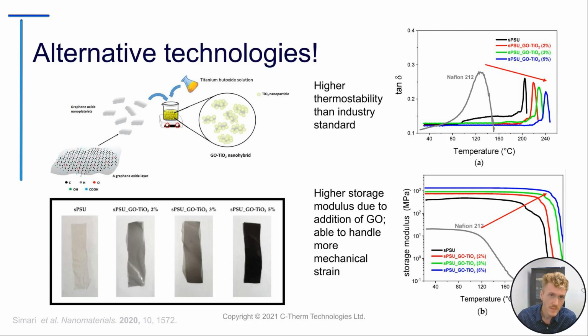So what they looked into is some sulfonated polymer, and more or less doping these sulfonated polymers with graphene oxide and titanium dioxide nanoparticles. By varying the amount of these dopants into the sulfonated polymers, they're able to achieve various degrees of proton transfer in these stack-ups. They wanted to look at the thermal stability of these materials by performing DMA, by monitoring tan delta in DMA experiments, by sweeping a temperature from around room temperature all the way up to about 250 degrees Celsius. What they noticed is a dramatic shift with increasing dopants leading to higher thermal stability and much higher thermal stability than that of the industry standard.